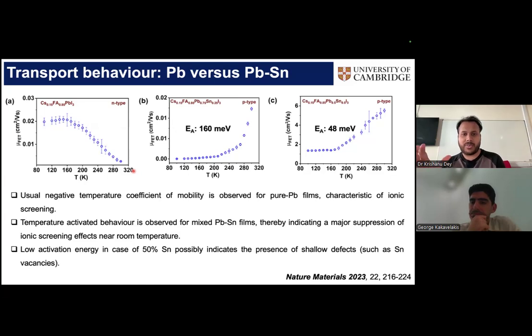And if you do a kind of a fitting of that positive increase part of the curve with the Arrhenius equation, you can find the activation energy, and we can find that our best composition, which is the 50-50 lead tin composition, has a pretty low activation energy, suggesting presence of shallow defects. And looking at the literature, we know that these tin-containing perovskites contain a great amount of tin vacancies, which are believed to be shallow. So this might be a way of seeing that in our temperature-dependent measurements.